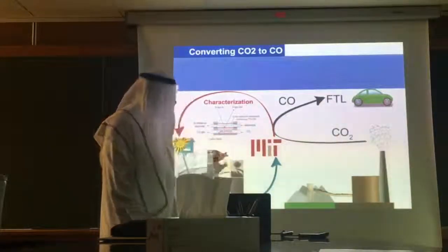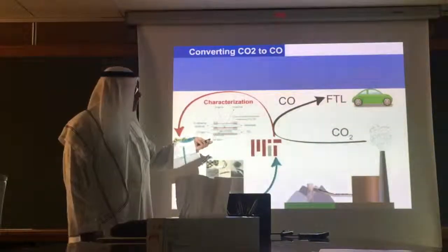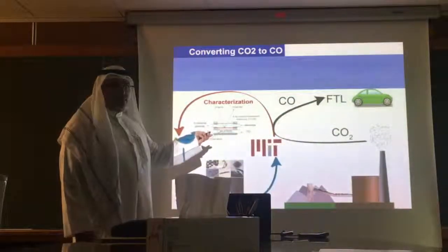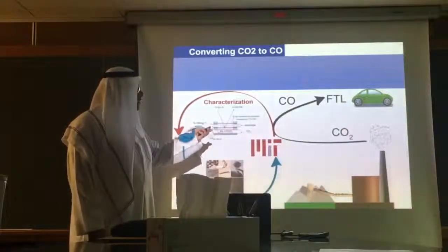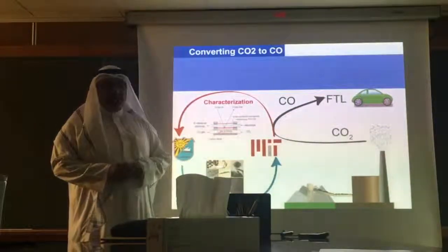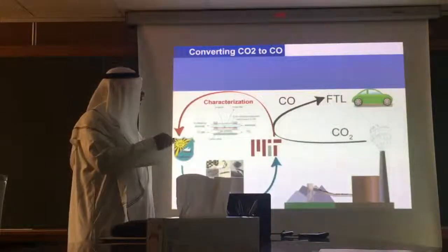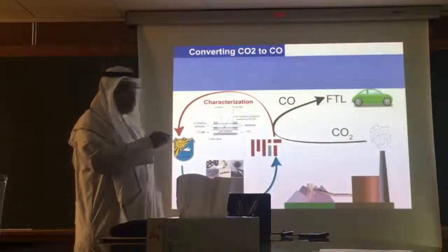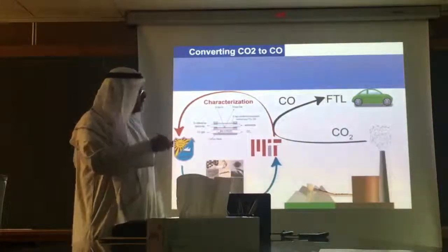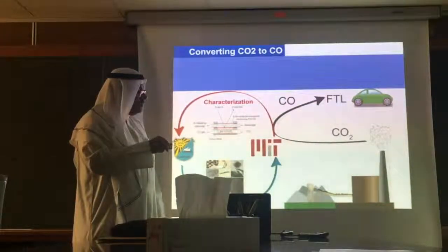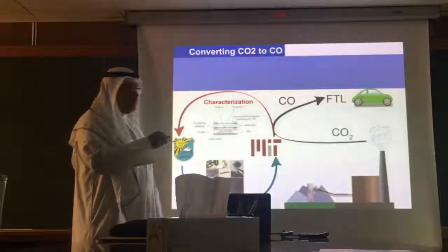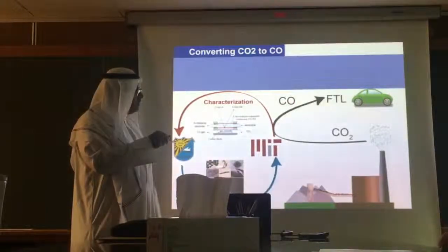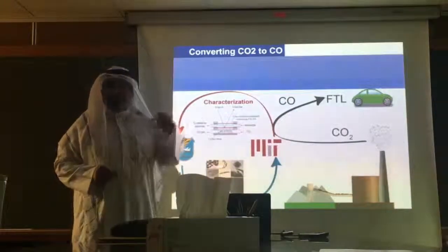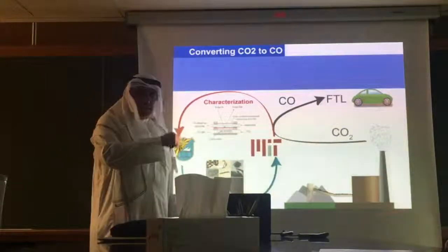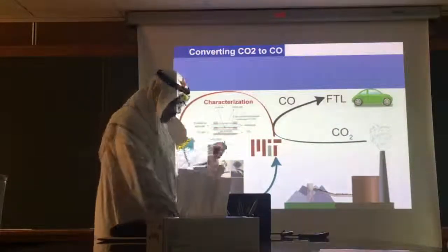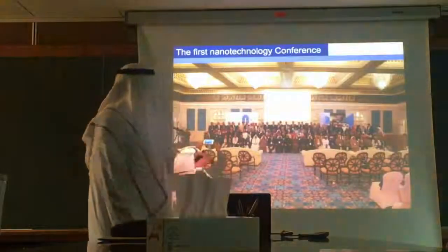This is converting CO2 to CO. And you might think this is not good for the environment, but CO is actually very useful. You can convert the CO to methanol after that, and methanol is a biofuel. So instead of just releasing the CO2 from our factories, we convert it to carbon monoxide, and then we convert it to methanol that we can use as fuel. So it's actually recycling the CO2. I did this work, and we published it.